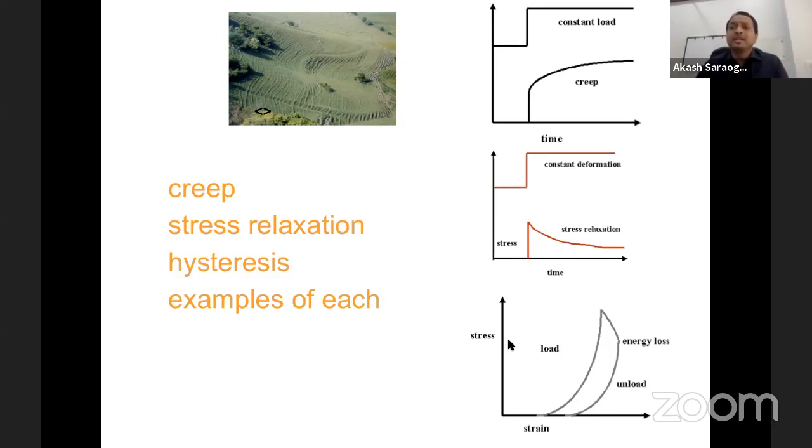Now, when we use an Exeter stem in cemented hip arthroplasty, we have put the stem inside, which means that we have put a particular load or stress into that bone for a particular amount of time. After a few months or years, we see that the stem subsides. And this is a typical example of creep. The load is constant. That does not change. The Exeter stem weight or the load is going to remain the same.